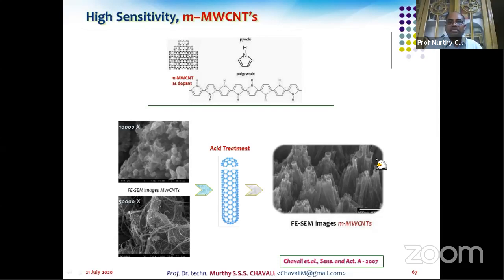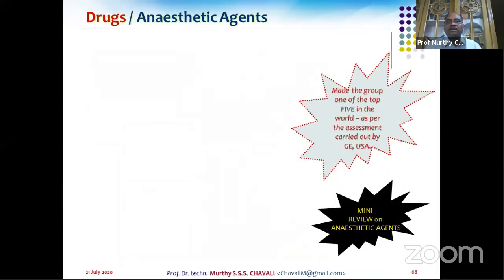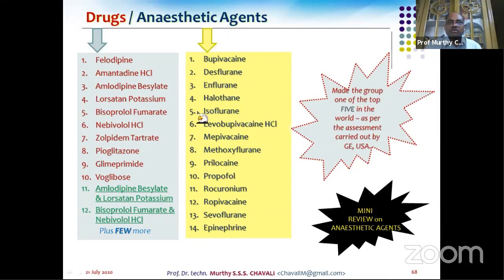So we typically gave an acetic acid treatment for 1 day, and then we were able to cut the heads of the multi-walled CNTs and enhance. This is the typical picture where we use modified multi-walled CNTs to detect or sense, enhancing the signal by 10% of our requirement. So in this way, we are trying to modify physically, chemically, functionalize them, and so many other things. And finally, this is a list of things that we have done. These are the things we got from GE to develop sensors. We were able to develop up to 7. The rest are still under work.